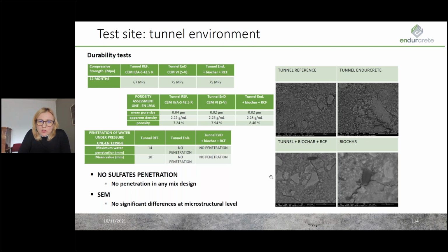The porosity measurements showed very similar results with a very high number of pores, but the mean pore size around 0.04, 0.02 micrometers, which means a very high resistance to the frost. And as well, the penetration of the water was much better, or no penetration at all recorded with the tunnel EnDurCrete concretes, as well with the addition of the biochar, comparing to the tunnel reference concrete.